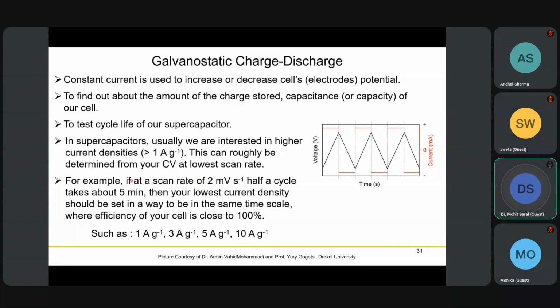In supercapacitors, basically we are interested in very higher current densities, and we can calculate which current density to choose based on our cyclic voltammetry data. This is one example. Let's say if your scan rate is 2 millivolts per second, and basically half of the cycle takes only 5 minutes, then the lowest current density you choose will be in the same time scale where your efficiency is 100%. So basically you can calculate how much time is changing, and we can insert the value of current density accordingly. Typically we use current densities like 1, 3, 5, and 10.